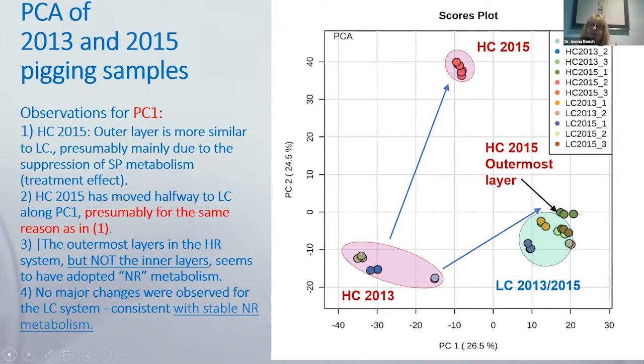So basically what all these mitigation strategies were able to do was change the outermost layer of the corrosion products, but not really change the population or metabolomics or shift it into a low corroding system. So one could, by intervention and by intelligent strategies, change the behavior of these populations to shift them towards a less corroding or non-corroding or just normally corroding environment, but not really when one looks into the populations and materials that were closest to the pipe surface.